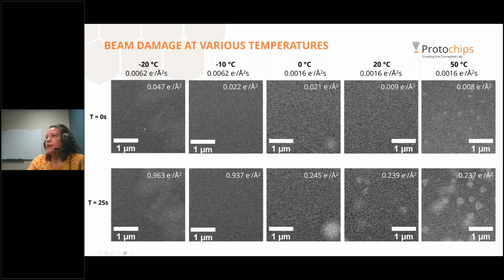We do see that there is a decrease in the amount of beam-induced irradiation despite having way higher, more than 3 times the amount of dose rate, as well as cumulative dose. So I don't label this. The top here is the dose rate, and what you see overlaid on the image is the cumulative dose, meaning the amount of dose at each pixel inside of the image itself. The top row is time 0, bottom row is after 25 seconds of dose of imaging.